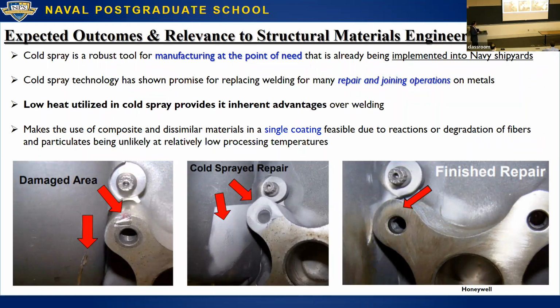And kind of big picture, just to wrap up, we know that cold spray is also a very useful technique where it's a portable technique. It can be used at the site of need to repair these structures. And what we're trying to do is come up with the next generation of materials and demonstrate it in a scalable fashion. So when we make this new aluminum boron nitride composite, we can show, hey, it has useful properties. And by the way, we're able to make this material in the same exact ways that we envision the end use application, which is by cold spray. So we've actually patented some of these compositions, and we have this path forward for how to transition the technology, because we are using the same processing route that we actually envision for the application.